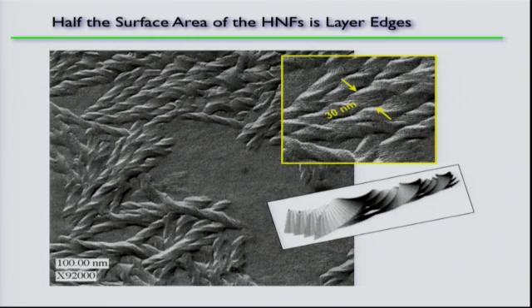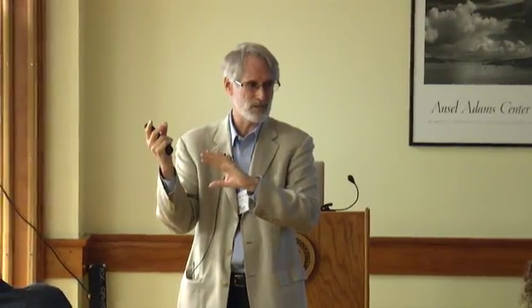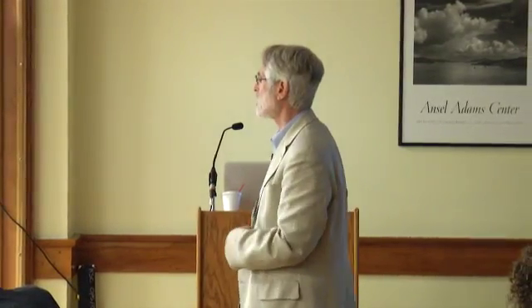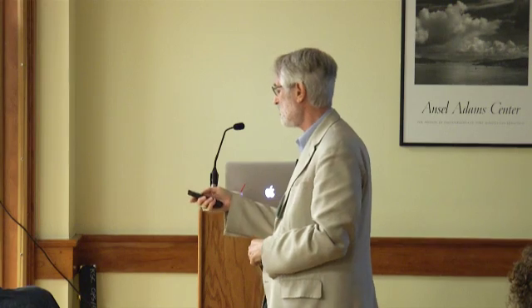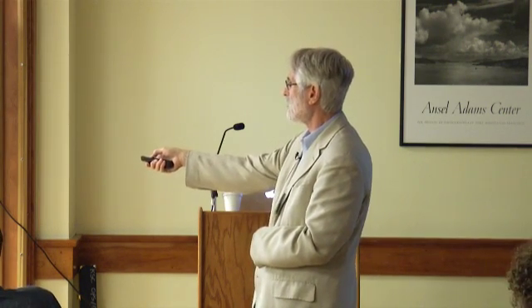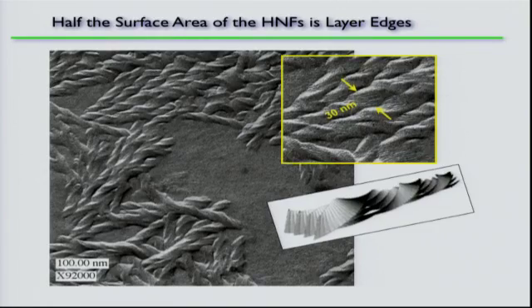So, here's this TEM image of these helical nanofilaments. Here are the edges of layers. Here's C9 hydrocarbons sticking out like a self-assembled monolayer. And so half the surface area of this thing is edges of layers. So I'm telling you we have a liquid crystal phase of nanocrystals that are about 30 nanometers in diameter, 5 to 8 layers of these crystallized bent core molecules. The size of the squares is about 30 nanometers. And it's got this twist, and so that means that half the surface area is layer edges and half the surface area is faces of layers or C9 hydrocarbon.